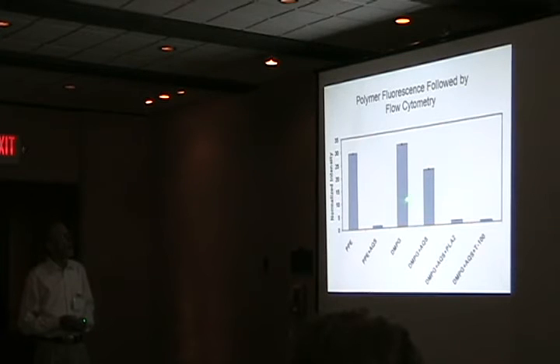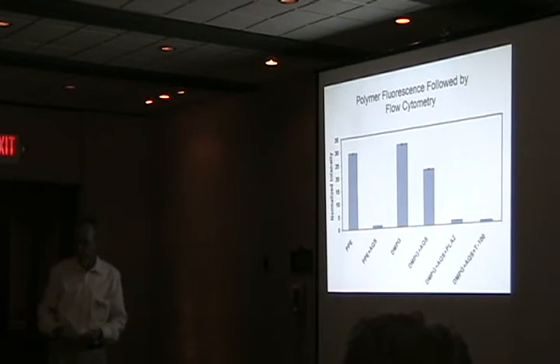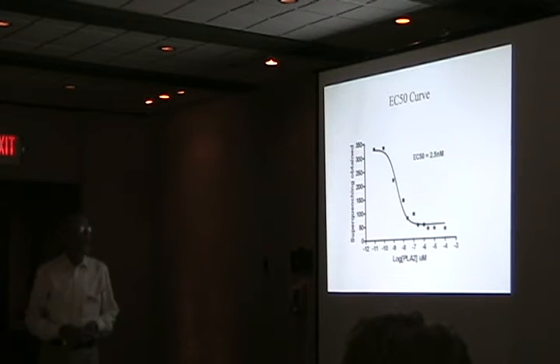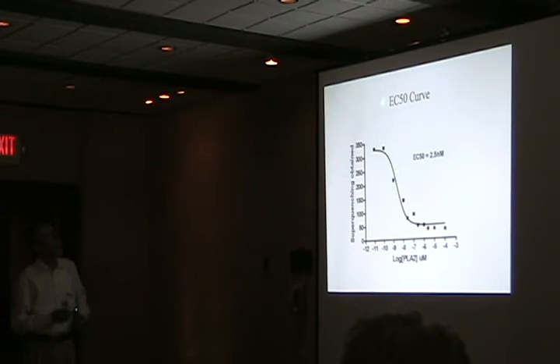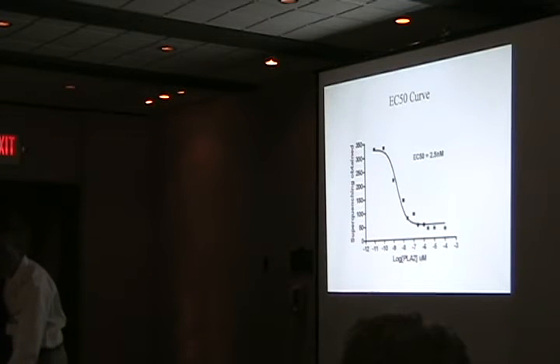Now, if we take the beads that have polymer and DMPG on it, and then we add the phospholipase, and then add anthraquinone, you can see that we have comparable quenching to what we have for the polymer itself. So clearly, this is a good assay for the activity of the phospholipase. In fact, what we can do is run an EC50 curve for this reaction, and what we get is an EC50 of about 2.5 nanomolar for the phospholipase, which compares very well with what we find in the literature, right around 2 nanomolar.